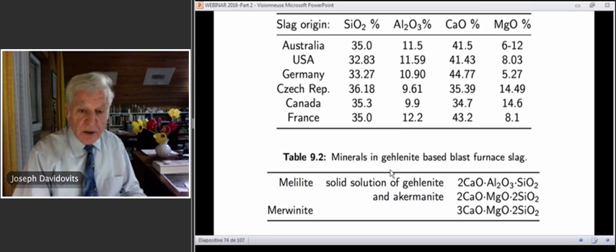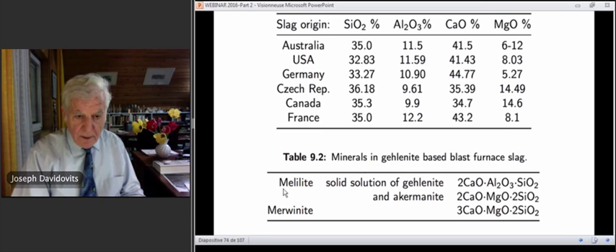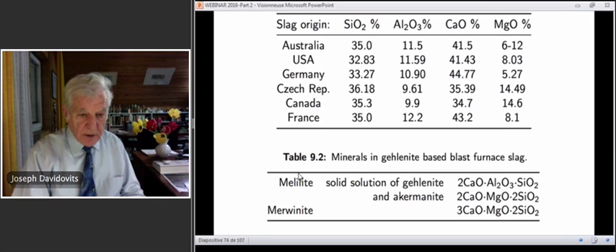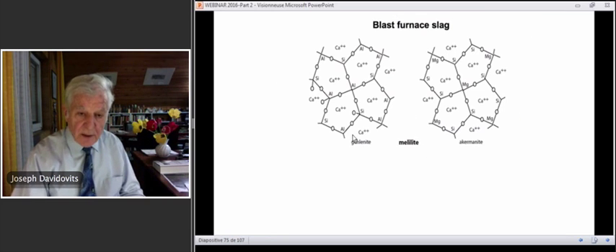If we look at the minerals that we have in the slag, one, that is the major part, is called the melilite. This is a solid solution of gehlenite, which is calcium aluminum silicate based, and akermanite, calcium magnesium silicate based. These are minerals, and if you look at their polymeric structure, this is the melilite, gehlenite: aluminum, Si, oxygen, aluminum, and then the calcium cation in between.